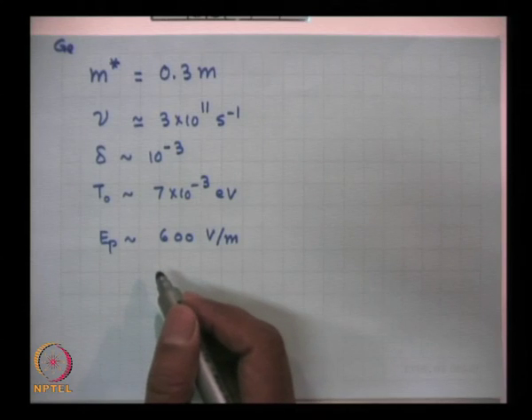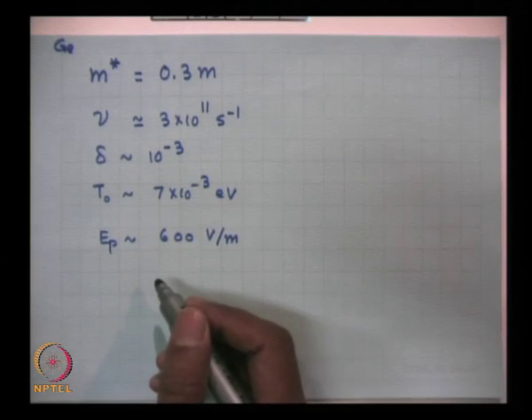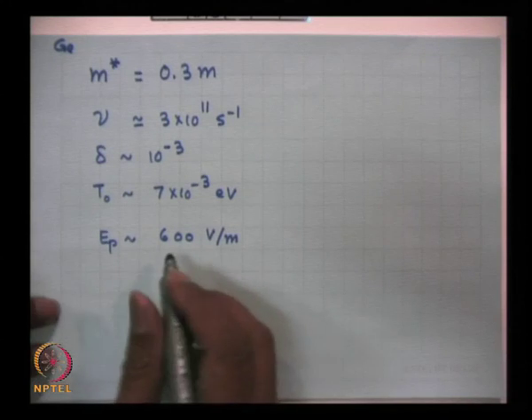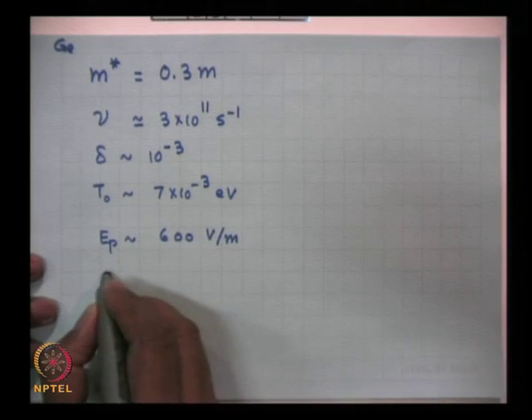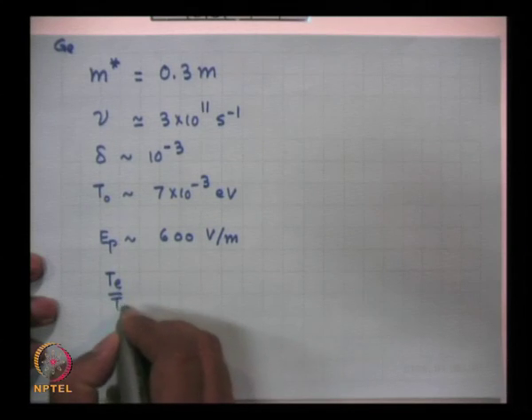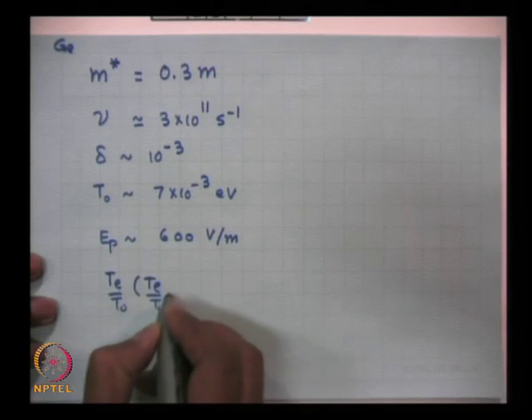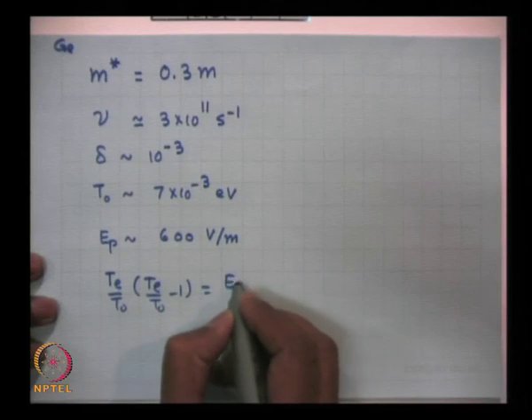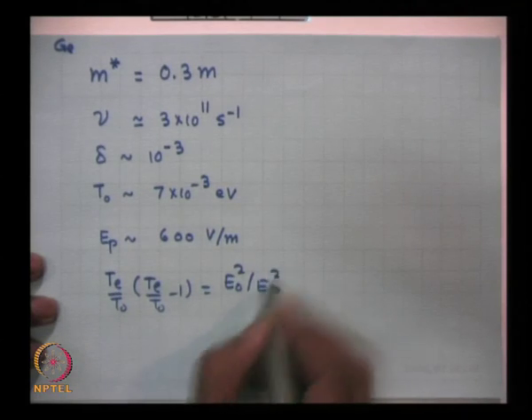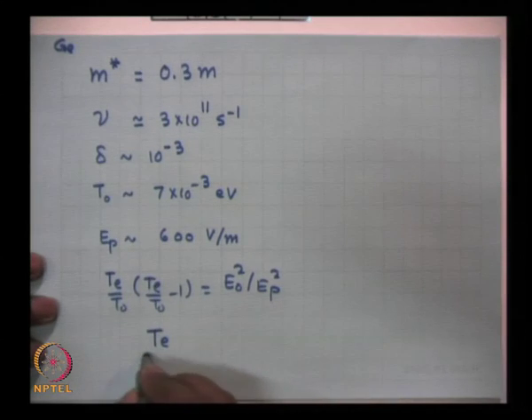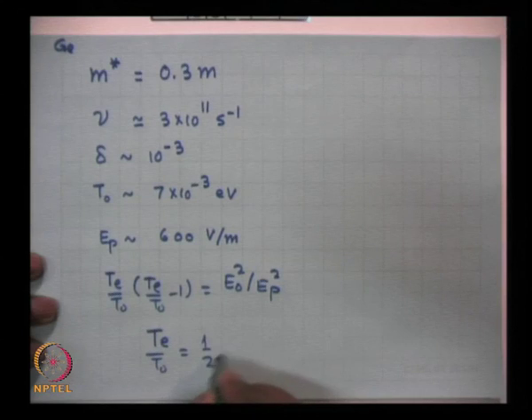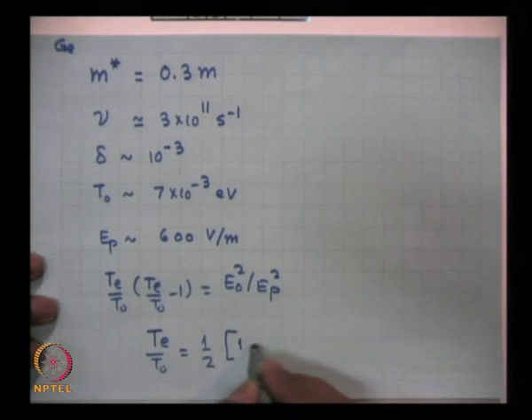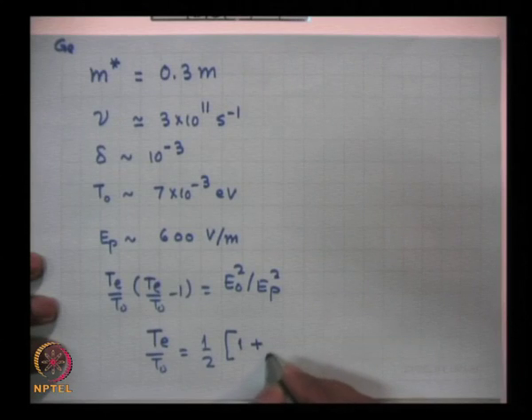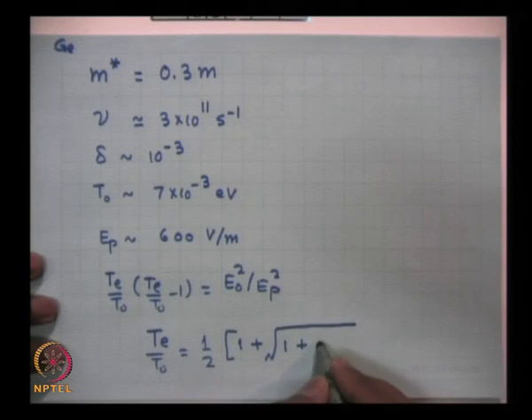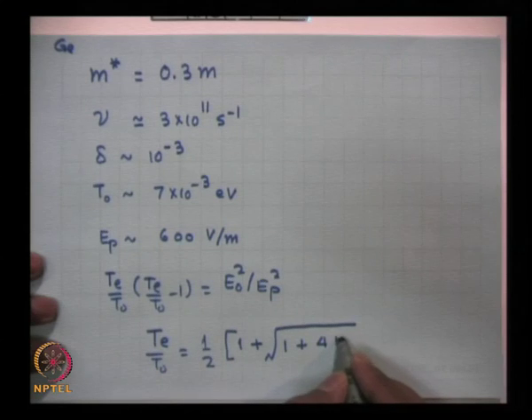You will be able to achieve this condition, and hence the electrons will acquire a temperature higher than the temperature of the lattice. Now, what is the solution of this equation? The equation was Te upon T0 into Te upon T0 minus 1 is equal to E0 square upon EP square. If you solve this, it turns out to be Te upon T0 is equal to half of 1 plus under root 1 plus 4 E0 square upon EP square.